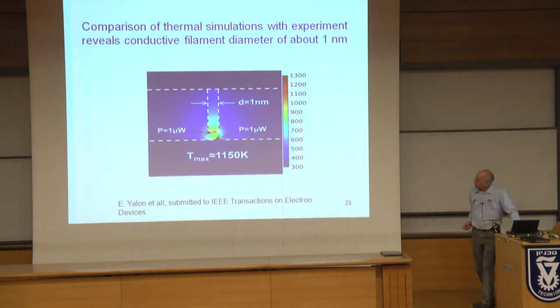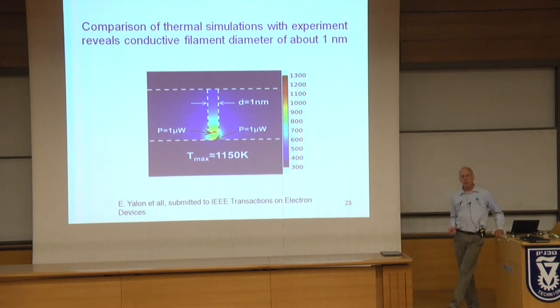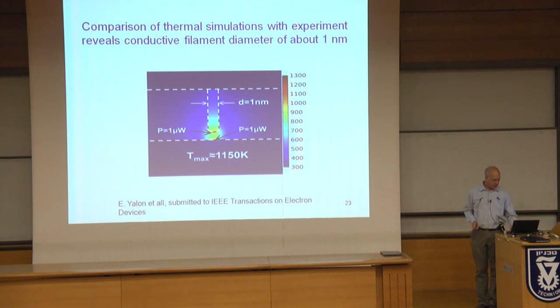These are the results of our thermal simulations, and we compare the thermal simulations with the experiment. Our main goal here was to try and evaluate the diameter of the filament. It turns out that although these simulations are not very straightforward and there are many complications, the result is quite robust to the diameter of the filament, so we're pretty sure that the diameter should be about one nanometer, which means that there are only several vacancies at the top of this filament, which I think is quite interesting. Thermal simulations by themselves are very complex, and there are several groups doing just that.